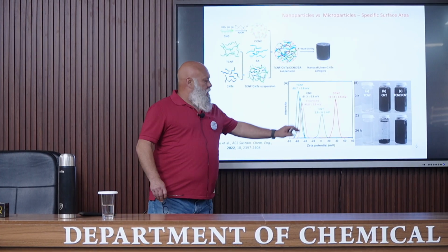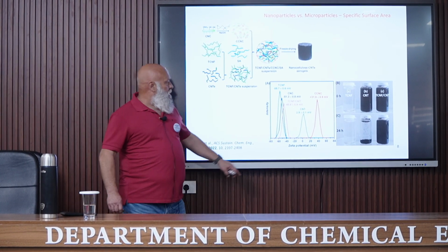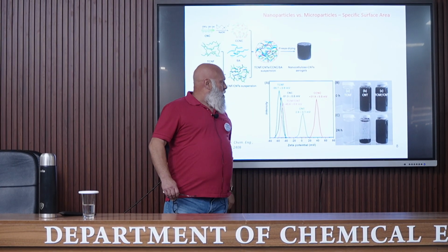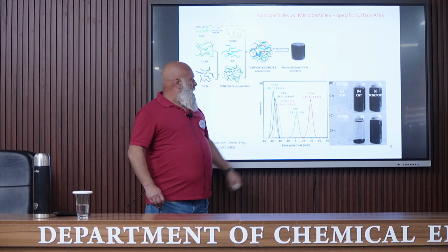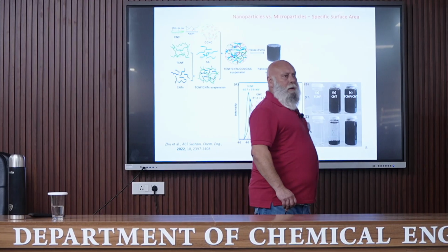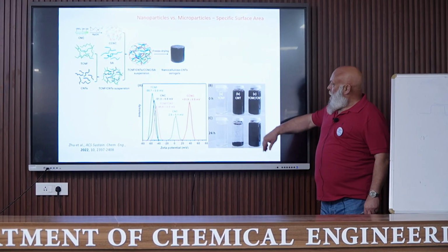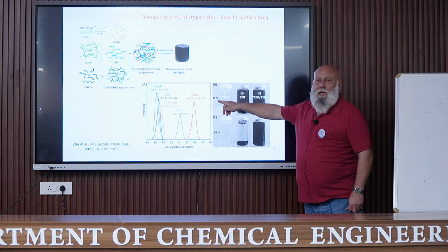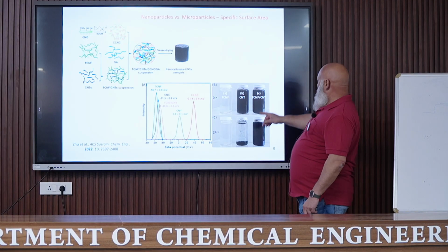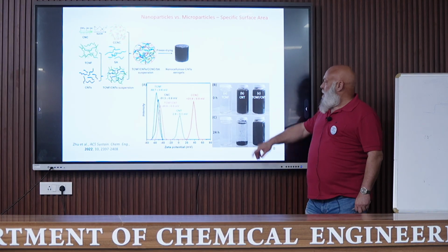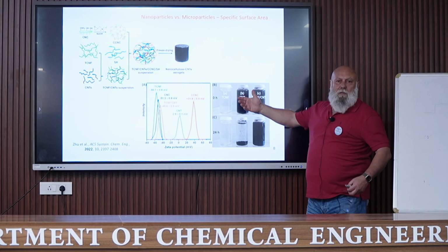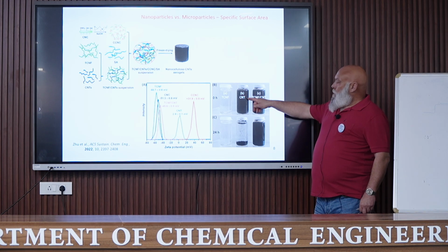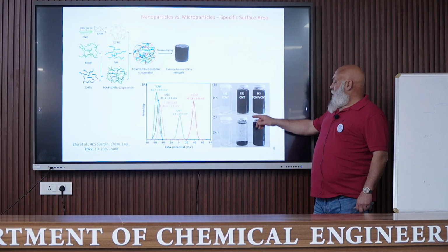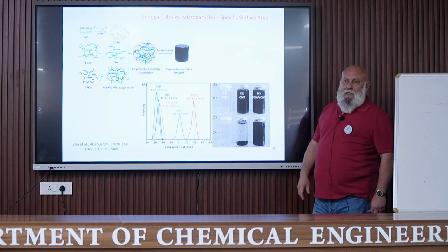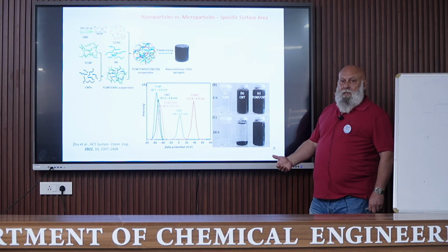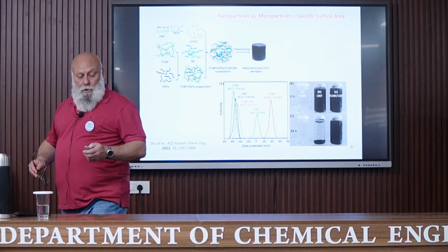So we can see from this zeta potential measurement the interaction between the different elements because cationized cellulose nanocrystals are positively charged and most of the other elements are negatively charged. And so it leads to some stabilization of carbon nanotubes. You can see here, this is a dispersion just after stirring or 24 hours later. I realized, yes, sorry, it is here. This is for TEMPO-oxidized cellulose nanofibrils. You can see that the suspension is stable in water. Carbon nanotubes are not stable. We observe a sedimentation. And when mixing TEMPO-oxidized cellulose nanofibrils and carbon nanotubes, we can see that we can promote the dispersion of carbon nanotubes.